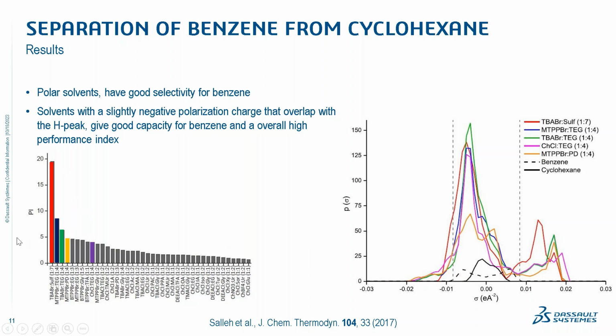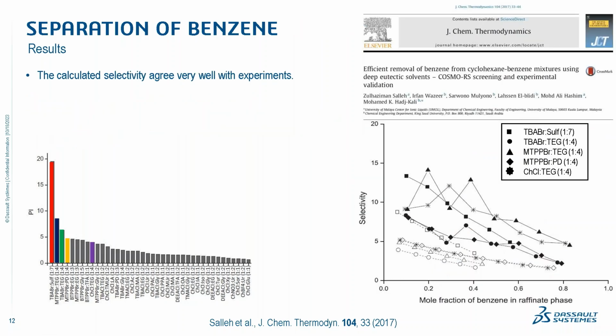So here we have then identified a set of good candidates, and we can then perform experiments to compare. We can see here that the selectivity in the experiments are the full symbols, and the open ones are the simulation. So we can see that we are having quite good tendency and agreement here, showing that these candidate solvents are also confirmed by experiment as good candidates for liquid-liquid extraction for this reaction. So this is then an interesting, good example of how you can use COSMO to screen and to find suitable solvents.